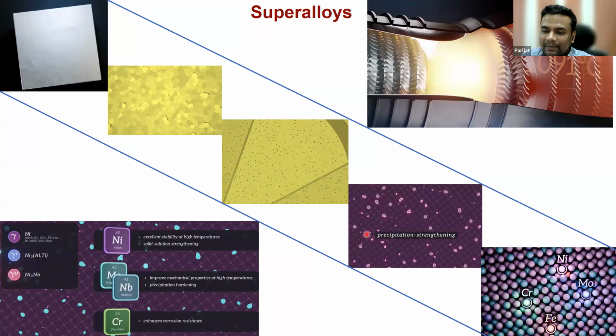Okay, so this is very much important, because how much precipitate do you want, what is the size, what is the type, all these things, as a metallurgical engineer or a materials engineer, we have to tune. That size, morphology, all these things, to give rise to a better property. And if you take this small square box and see it in a transmission microscope or some advanced microscopic technique, you can see that these nickel, chromium, molybdenum, iron atoms are arranged like this. So from atomistic scale to a bulk macro scale, these are the sequence of events that are happening and that give rise to this excellent strength at higher temperature of this nickel-based superalloy.